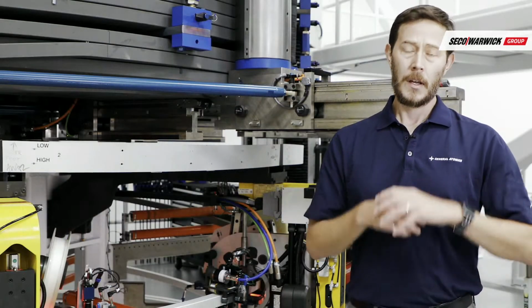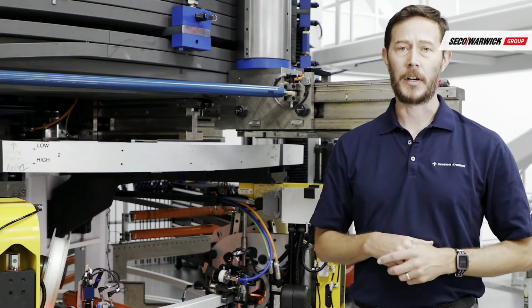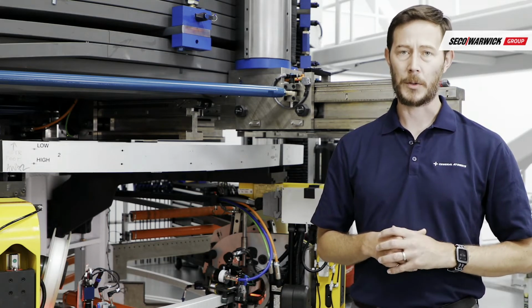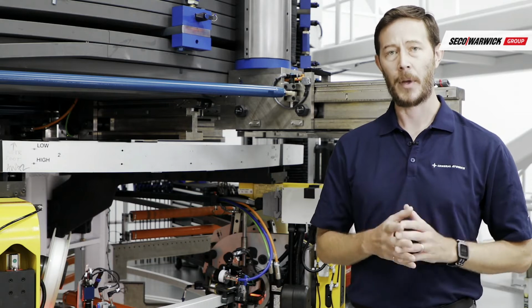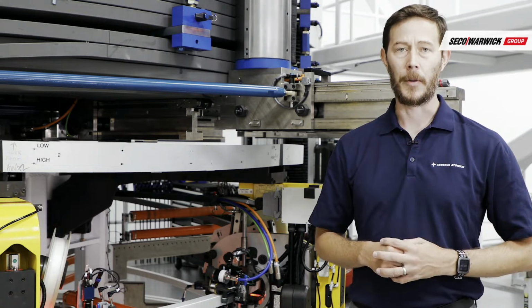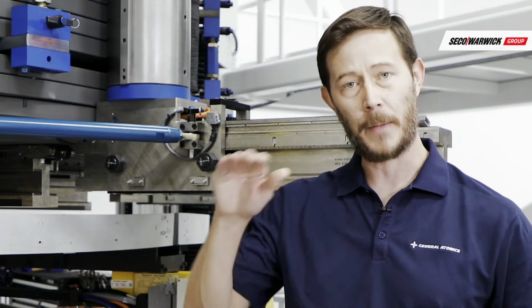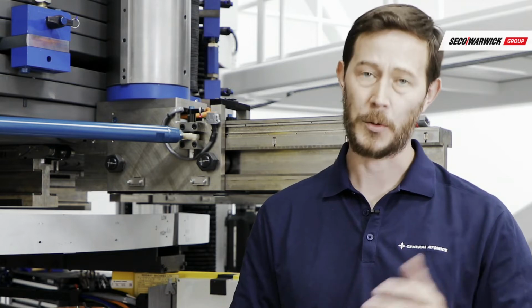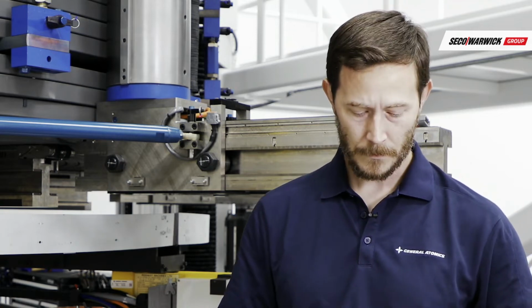So what is special about our reaction heat treatment process? The process that we use involves using fans inside of our convection furnace to force pure argon around the module to slowly and uniformly heat it up and allow the superconductor to form. The module is ramped up in temperature to 570 degrees Celsius, where it's held for about 10 days. After that, we ramp it up to 650 degrees Celsius, about 1200 degrees Fahrenheit, and it's held there for 4 additional days. The whole heat treat process takes 5 weeks.